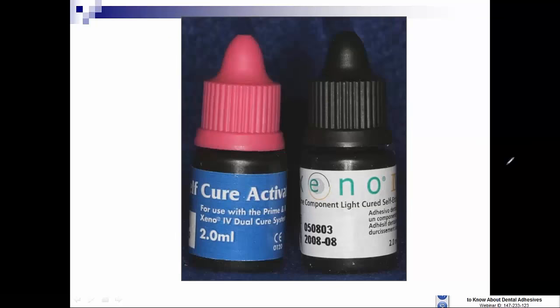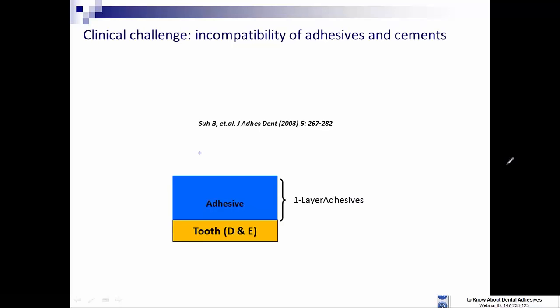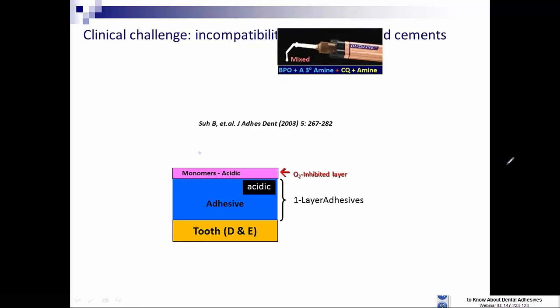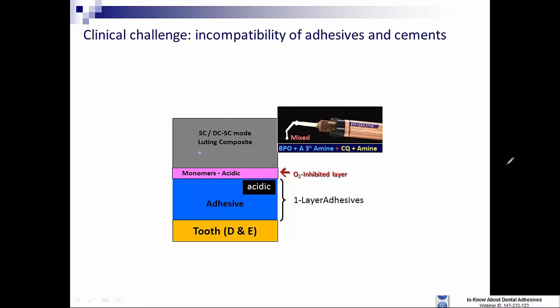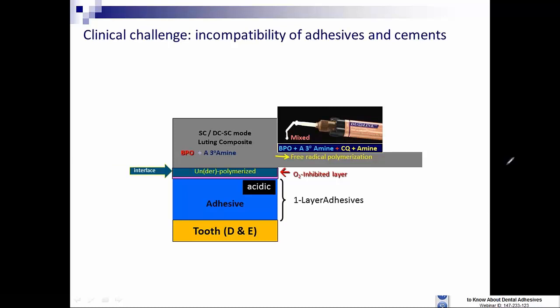Also, the dual cure activator that's used in this particular example with Xeno-4 and is also used with PrimaBond Elect. If we have a self-etching or an acidic adhesive on the tooth, that acidic adhesive produces an oxygen inhibited layer that is acidic. And when we place on top of that a dual cure luting composite that is typically cured with benzoyl peroxide and a tertiary amine to promote free radical polymerization, well, the tertiary amine is a base, and the acidic interface then becomes underpolymerized because it inhibits the total polymerization that's driven by this chemistry system, which means careful attention to matching your resin cement and the adhesive system and following directions of the adhesive system when using an indirect technique is critical for maximum success.